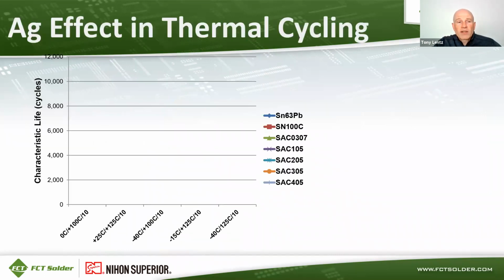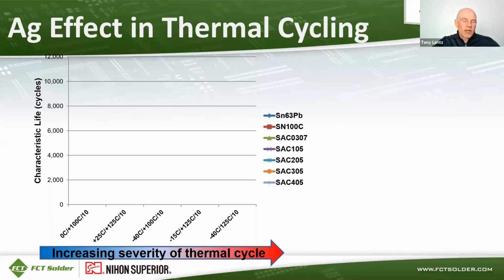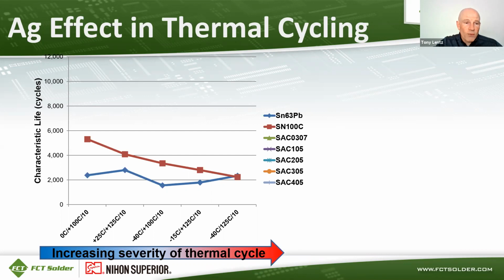Silver has an effect in thermal cycle testing. So this is a chart of characteristic life on the y-axis, and then different thermal cycle methods on the x-axis, with increasing severity from left to right. So on the left, we have 0 to 100 C, and on the right, that goes up to -40 to 125 C. This first plot is for tin lead alloy as a baseline, and that holds its characteristic life throughout all these different thermal cycles. And then we have SN100C, which starts off with a relatively high characteristic life with the easiest thermal cycle, and then that decreases with increasing severity of thermal cycling.